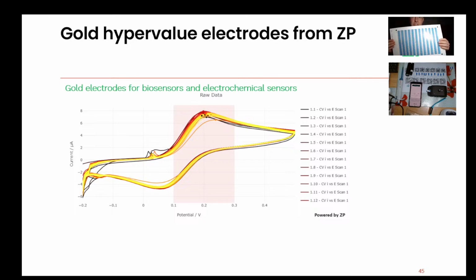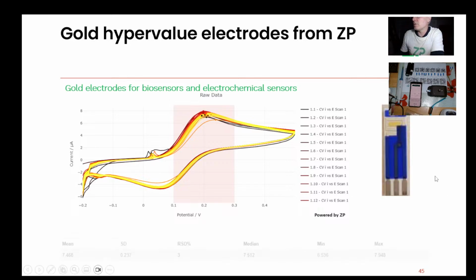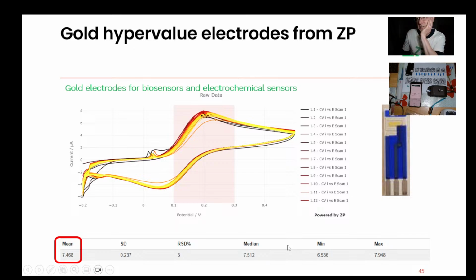like this, and we'll actually sacrifice quite a few per sheet to make sure that the sheet is generally good. And something that we really aim for is repeatability. So you have said it in your question. I think the biggest problem you possibly have is repeatability. So what do we do? We test the peak heights. We look at the standard deviation of the peak heights. We look at the relative standard deviation of the peak heights. And we're looking for an RSD that's in single digits.